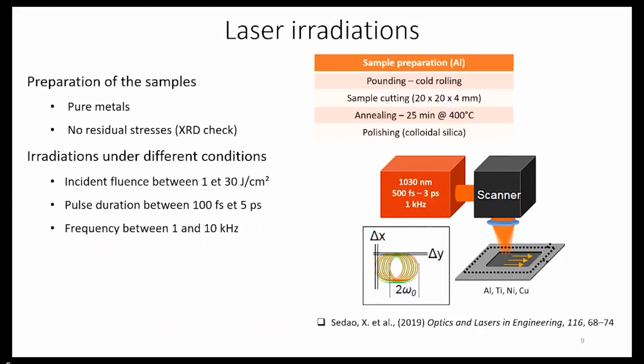Then let me present the methods for laser irradiation. We're using pure metal samples, almost pure, and we prepare them by cutting and polishing in order not to have any residual stresses, which we check with XRD measurements. Then we irradiate them thanks to a scanner in order to irradiate the whole surface of the material, playing with the parameters which are fluence and pulse duration. Then we do some control measurements, including ablation depth and surface roughness.